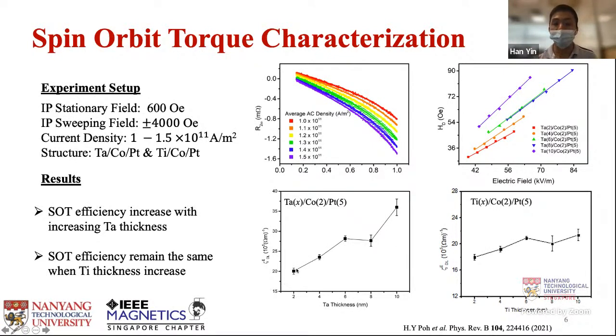And this is nothing special since Ta is a relatively strong spin source. Hence, the tendency to see an increase in SOT is no surprise. On the other hand, we observe a negligible change in SOT efficiency when we increase Ti thickness, since Ti has negligible SOT as reported from other literature. This SOT mainly comes from the Pt source itself.